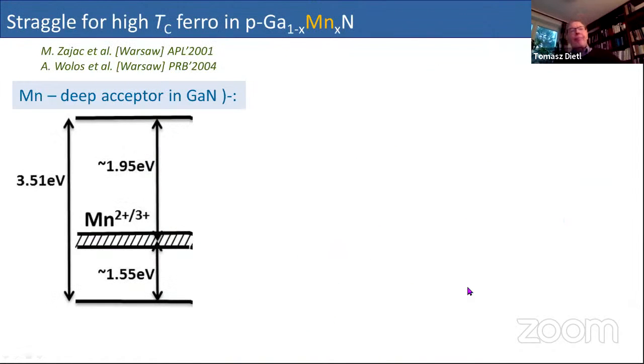So now we turn to another material, gallium manganese nitride. It's another example of dilute magnetic semiconductors where there are not too many carriers. And actually, people were looking at this material for a reason some of you may know, to see room temperature ferromagnetism in p-type samples. So people were looking for acceptor doping. Manganese was supposed to be an acceptor. Indeed, manganese is an acceptor in this material, but a very deep one.